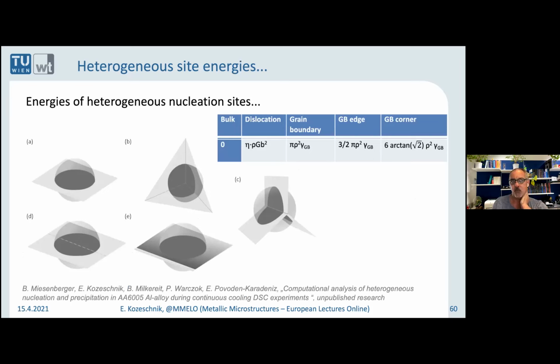But what we realized in analysis of the data was that nucleation of this Mg2Si phase occurred on the dislocations. And to be honest, it occurred predominantly at the grain boundary corners. So what we did was simply think, okay, when a phase forms on the grain boundary, like this one here, then the phase will remove this area of the grain boundary, the dark area. And that's an energetic advantage.